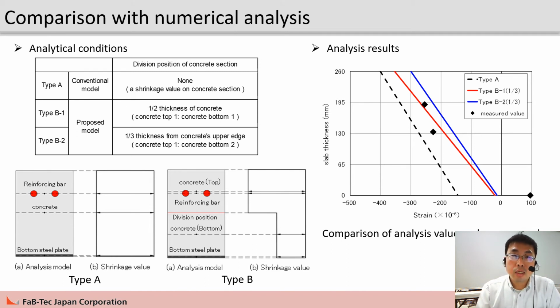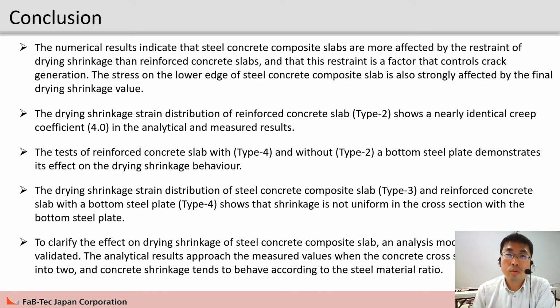The shrinkage strain of the upper reinforcing bar and concrete of the proposed model are nearly identical with the measured value. Finally, I will conclude my presentation. The drying shrinkage of the steel concrete composite slab was investigated by numerical analysis and drying shrinkage tests. A comparative study was conducted to clarify the effect of the bottom steel plate, and the analysis model is proposed. The conclusions are summarized as follows.